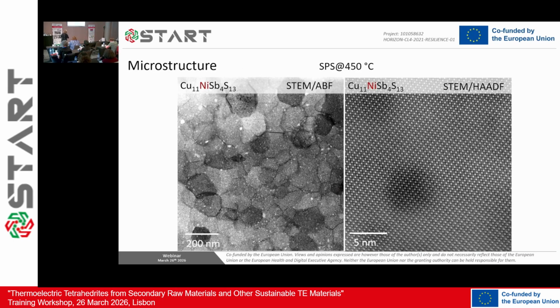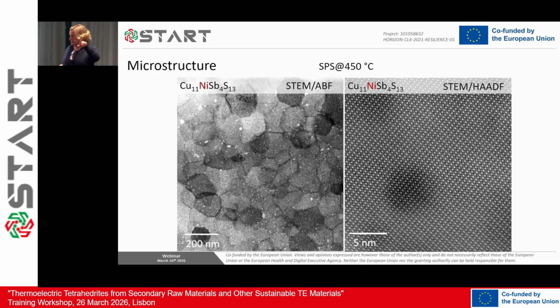So now if we try to zoom in with TEM—they were produced while we were studying the effect of nickel—what you see, these very small white dots here, are pores. If you increase the magnification, you see the pores more clearly. This is a HAADF image. I'm not going to explain what it is, but what you're seeing is that the heavy atoms are white, so when you see something dark, it's because you have less mass.